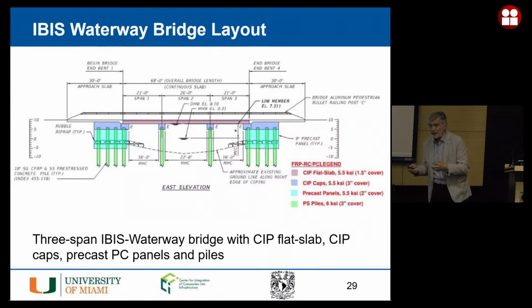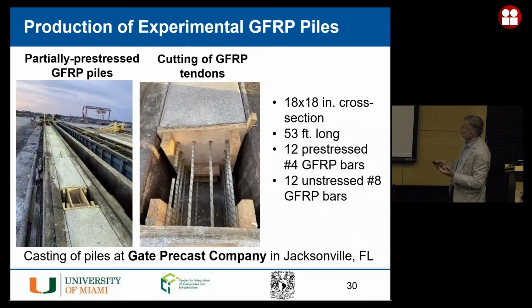Okay? Because you can stress the carbon at 70-75% of ultimate, so you can reach the same level of capacity that you have with the conventional 7-wire strands. And so that's why. But in this case, and I'll show you, we also did 3 piles using the glass, and we call that mild pre-stressing, because you can only attain 40% of ultimate because of a phenomenon called creep rupture.